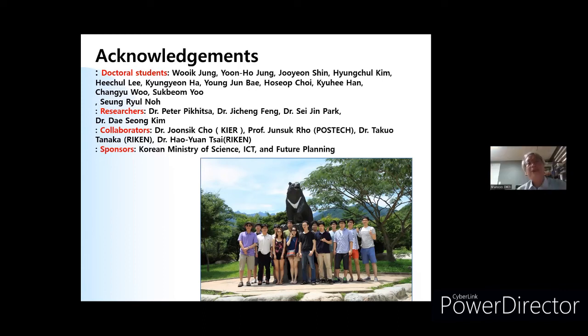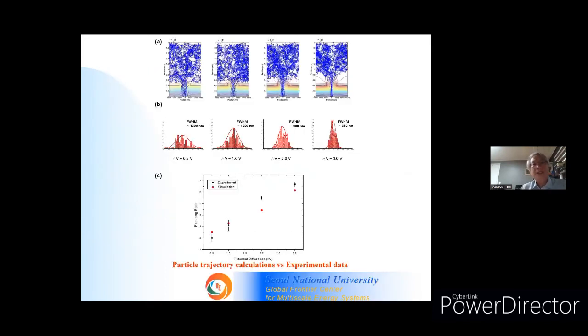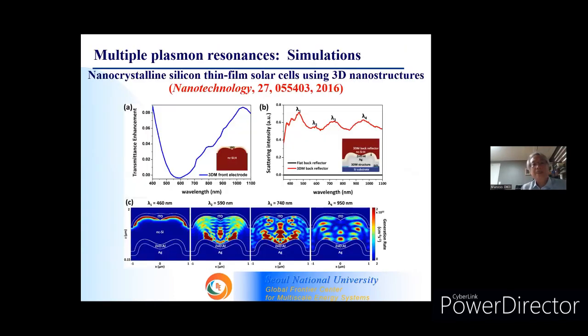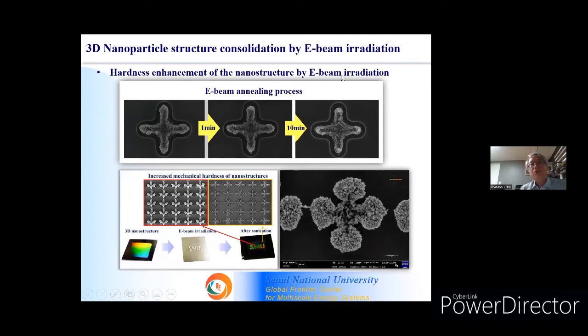Okay, I want to answer your second question first. Of course, the nanostructures are held together by van der Waals force, but you can enhance the strength by using electron beam irradiation. After you make the nanostructure, electron beam irradiation will sinter it a little bit to make it stronger. So even after sonication, these structures survive. Without this sintering, sonication will eliminate all the particles.